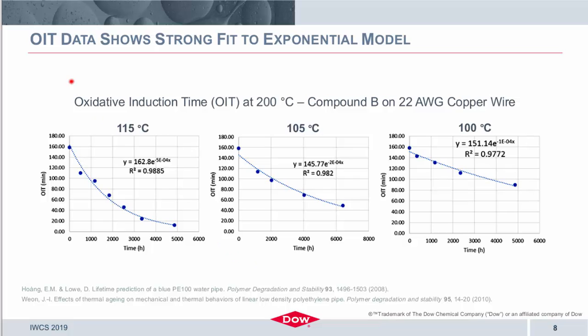So the first thing we'll look at is the OIT data that was generated. And what we found, similar to things that have been put out there in literature, is that the OIT has a strong fit to an exponential model. Here we're looking at oxidation induction time at 200 degrees Celsius on compound B, the 22 gauge wire for simplicity. All other compounds and wire gauges followed a similar trend, but what we'll cover throughout this next portion of the presentation is focused on compound B 22 gauge wire with 21 mil wall as a representative example for the others. What we're showing here is the OIT value on the y-axis versus aging time, aging at the different temperatures being 115, 105, and 100. The OIT was measured on the wire samples with the copper conductor included.